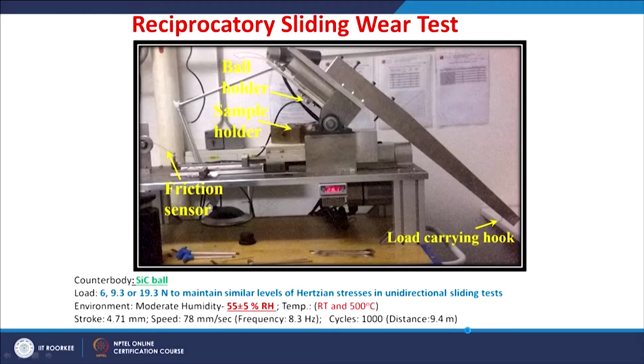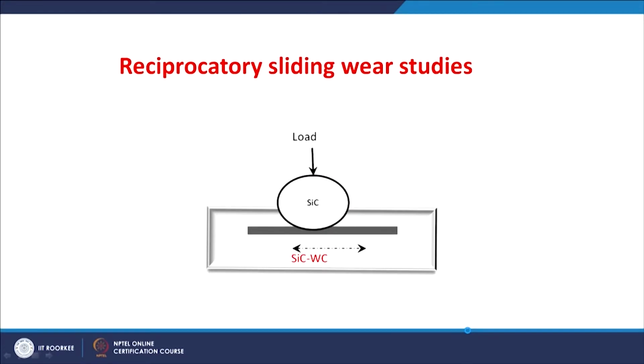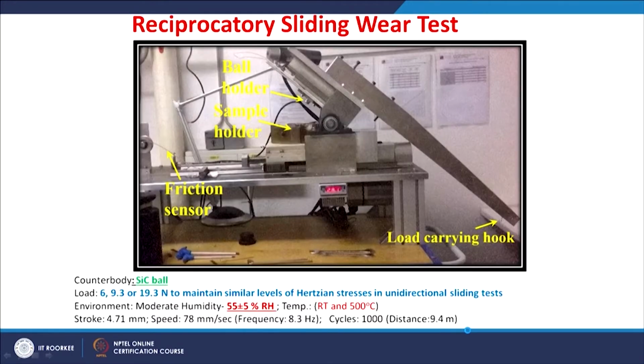Let us go to the last part of this lecture, the reciprocatory sliding wear studies. In order to understand the effect of the sliding mode from unidirectional to reciprocatory, we used a reciprocatory sliding wear test apparatus, where the ball was silicon carbide only and the load we changed from 6 to 19 Newton. These loads were selected to maintain similar levels of Hertzian stresses which were used in the unidirectional sliding test. So, these were done in moderately humid conditions at two different temperatures, room temperature and 500 Celsius. The major aim of this study is to understand the effect of the tungsten carbide content as well as the temperature of testing on the reciprocatory sliding wear behavior of the silicon carbide tungsten carbide composites.